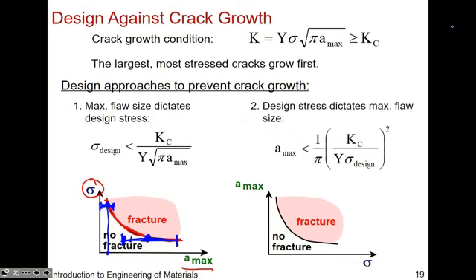Okay, so a stress versus crack plot. You could also flip the equation, and if you plot crack length versus stress, same thing. There won't be any fracture if your crack length is quite small and you also apply a small load. That's going to be your data point there. Probably not going to fracture. If you apply a lot of stress and your crack length is also really big, the material is most likely going to fracture. So you're just manipulating this equation, moving it around and just applying below or above the curve. Okay.